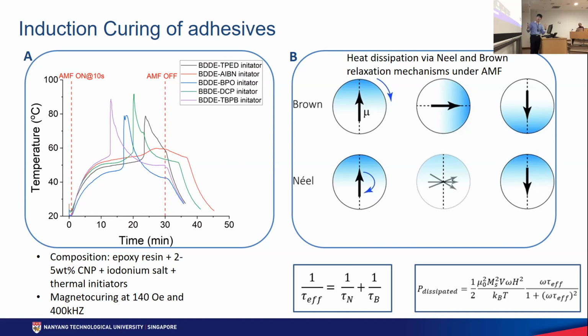The Brownian relaxation mechanism involves particle rotation, which induces shear stresses and dissipates heat. While for the Néel relaxation mechanism, we have reorientation of atomic dipole moments, and it has to actually overcome an energy barrier that's proportional to the magnetic anisotropy constant, and that dissipates energy as well. So these are two competing relaxation mechanisms, and overall, the one with the lower time length over here is the dominant mechanism. And we can actually calculate the amount of heat dissipated by this equation.